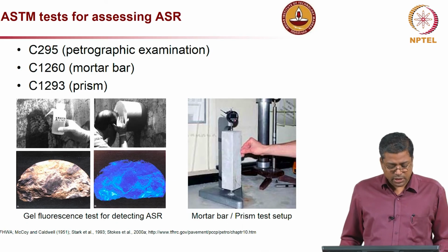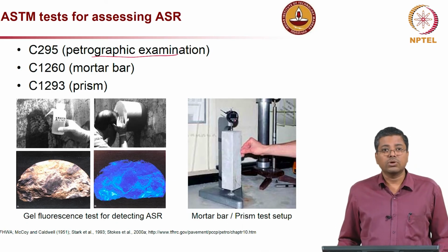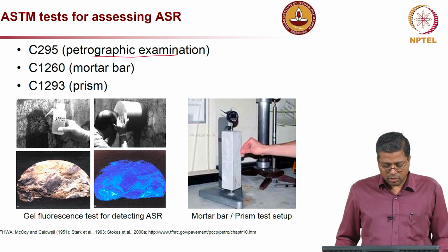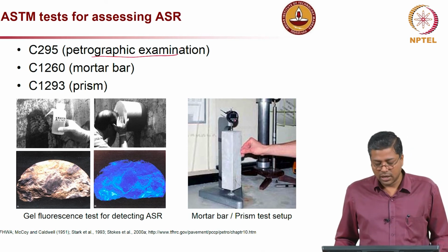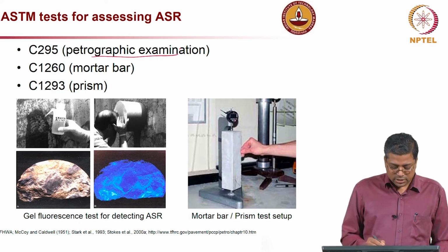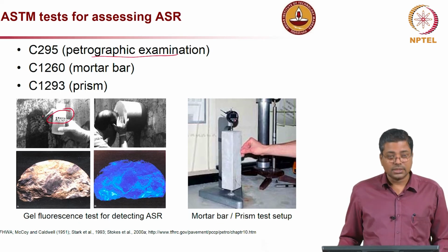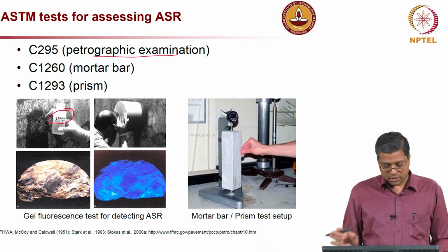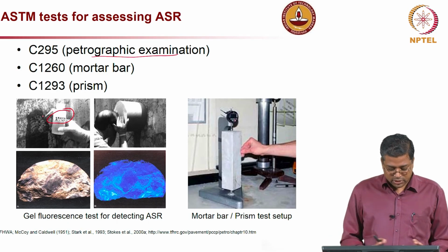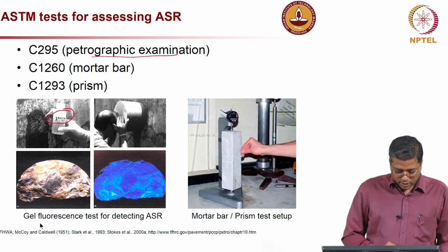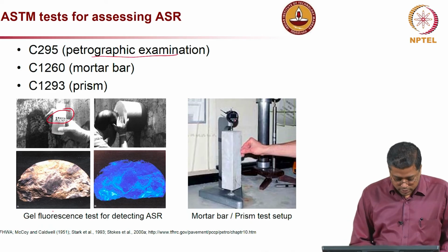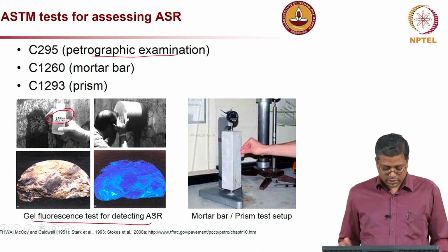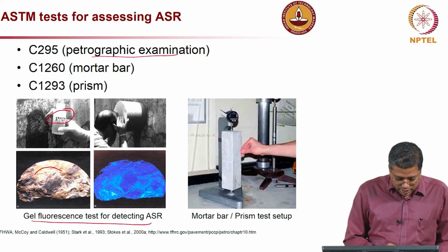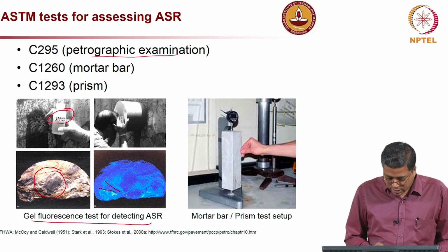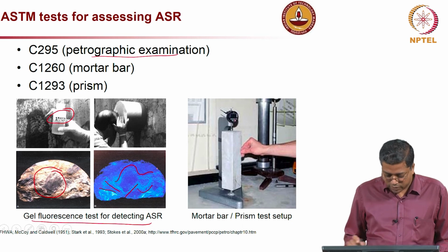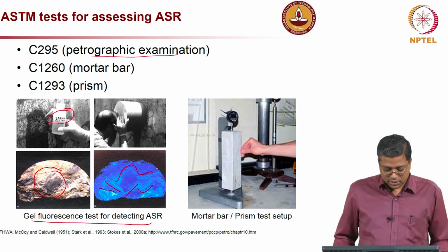I am just showing multiple tests here. The first thing is looking at the type of aggregate, or whether there is any ASR gel present in the system. This is one test where uranyl acetate is used. You spray this onto the concrete surface, and then you can look through and see the gel fluorescence test for detecting ASR. In this picture, this is the aggregate region, and you can very clearly see that around the aggregate you have a different color, and that indicates the presence of ASR gel.